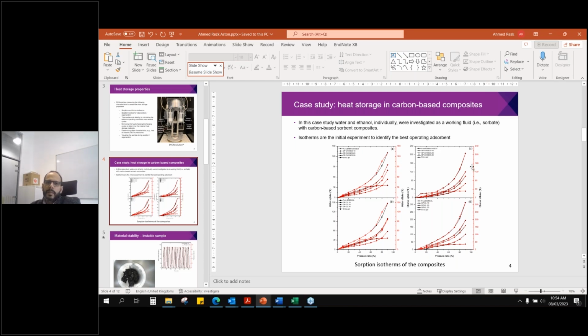One of the materials I developed uses some salts related to ionic liquids and some carbon-based material as a host matrix, and we tried to generate different composites. The variation between one composite and another is the concentration of the salt in the host matrix. Here we can look at the isotherm for the developed material, which is the first step to characterize the material. In this case study, I present this newly developed material working with water and ethanol as working fluids. The reason for using water is that water has a very high heat of adsorption compared to ethanol, but ethanol can be handled at sub-zero operating conditions.